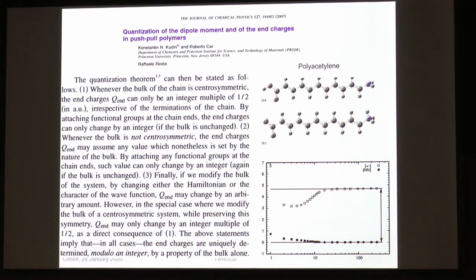One of the most interesting discussions of all of this, I think, is this paper and set of papers discussing these results, with Raphael as third author, looking at polyacetylene. So this is a one-dimensional case where you can solve the problem for both finite systems and for the infinite system. And you can show directly by Hartree-Fock calculations, which they did, that there are two sets of solutions, a zero solution for the centrosymmetric chain, and a solution with half a quantum. As you go to longer and longer chains, with chain length on the x-axis and polarization on the y-axis, it converges to these values that you get for the infinite system, depending on your surface termination. And what I want to argue is that this is, in fact, proving my point.